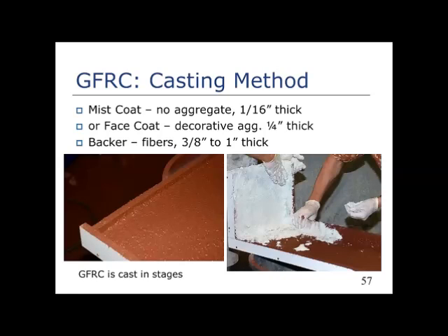If, as in the previous example of that aggregate with a 1/2 inch limestone, you take your mist coat and simply add aggregate to it and mix it up, you now create what's called a face coat. And that face coat is put in thicker. Usually it's about as thick as the average aggregate size, but typically it's about a 1/4 inch thick. You can't spray that, so you hand pack that into the mold. That would then be ground and exposed. So you either have a mist coat that has no aggregate or a face coat that does.